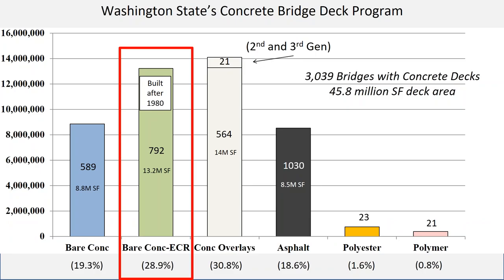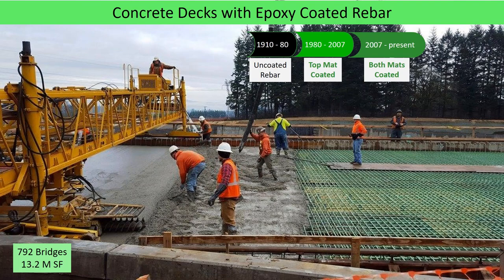So now, bare decks with epoxy coated rebar. So Anthony kind of went through a lot of this already, but the kind of the history of epoxy coated rebar, we had uncoated through 1980 in our state, and then we did the top mat from 1980 to 2007, and then we did both mats from 2007 to present. And we have about 792 bridges total in our state with epoxy coated rebar. This is important when we start looking at some of the details and seeing some of the deterioration. We can go back and kind of clue in on what was down on the bridge originally.